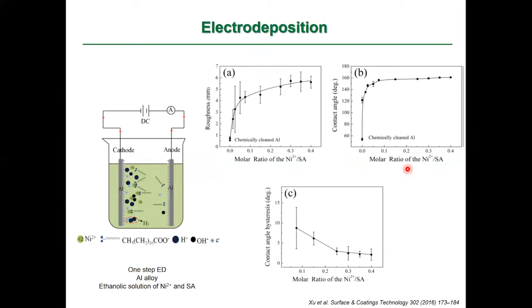See, this is a one-step electrodeposition process on an aluminum alloy, where they use an ethanolic solution of nickel and stearic acid. Stearic acid is a low surface energy component, and nickel is used for nickel plating to get more corrosion resistance. You can see in one step, and depending upon the molar ratio of the nickel and stearic acid, the surface roughness, contact angle, as well as the contact angle hysteresis or sliding angle varies. And you can see that under that particular condition, the superhydrophobicity is achieved by a one-step electrodeposition process.